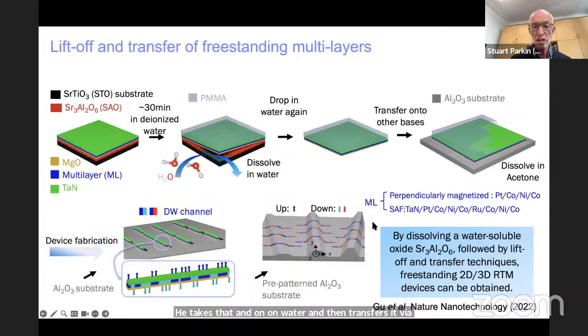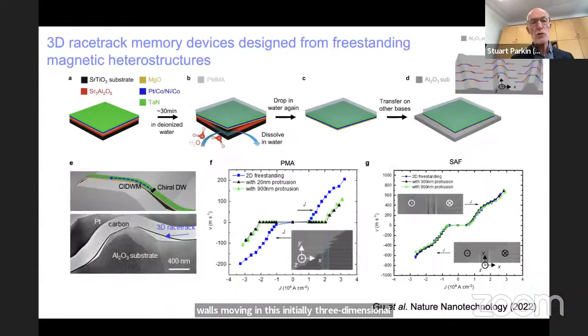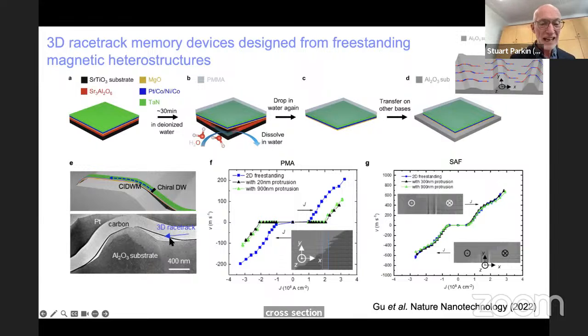And the base here, shown in this cartoon in the bottom, is a pre-patterned sapphire substrate where he's made these hillocks up to 1 micron tall. And then he basically transfers the membrane, which is now very flexible, and the membrane follows the underlying pre-patterned substrate. And he could see the domain walls moving in this now three-dimensional structure. What is shown here on the left in E, you can see a cross-section TEM of the 3D racetrack. You see that black line. It's only a few nanometers thick, and it almost nearly follows the sapphire substrate, but almost nearly follows. And that's what we see.